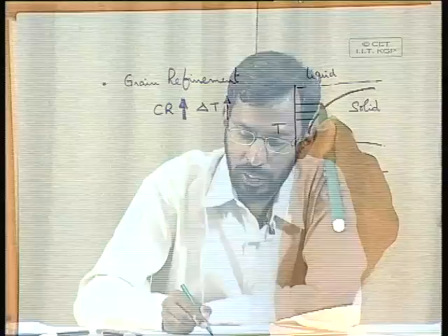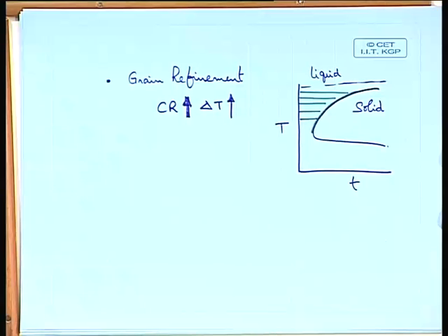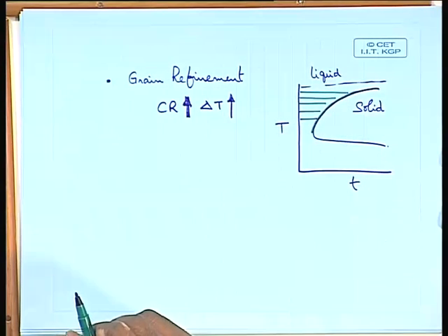like this as the temperature decreases, isn't it? So you need lesser and lesser time as you come to lower and lower temperature, and that is what we call the incubation period. So when you are cooling rapidly the liquid, the time available is very small.